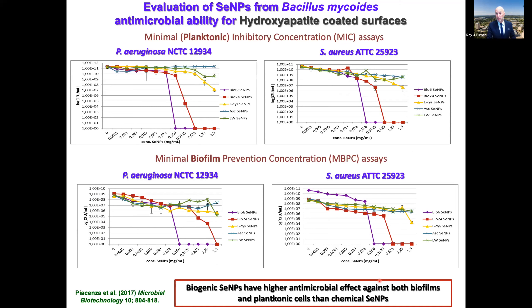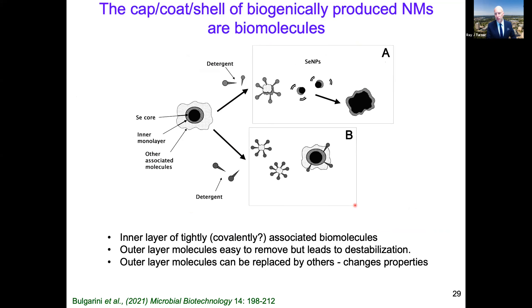Moving toward application: for medical indwelling devices such as joint implants and hip replacements, nosocomial infections are a major problem. We used a hydroxyapatite-coated surface — which is used so bone material can interact with the implant — and we want to prevent biofilm forming on this surface. Comparing chemically synthesized nanoparticles in various ways with biogenic nanoparticles, the biogenic nanoparticles were able to inhibit both Pseudomonas aeruginosa and Staphylococcus aureus from forming biofilm on these medical implants, whereas the chemical ones could not.